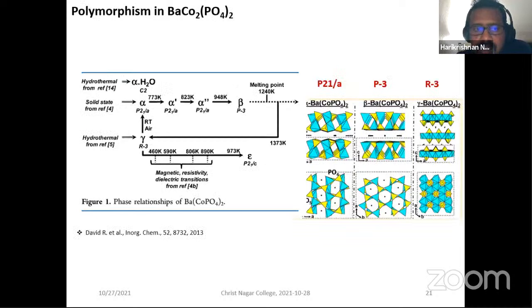Once you get the crystal, you want to look at how the atoms are arranged. One method is to shine X-rays and look at the diffraction data. Literature on this material says that it can have many different structural phases, meaning many different ways of arranging the atoms in space. Three of them are shown here, with three different space groups. We are interested in the third one, called the gamma phase. The other phases are not interesting because they have a very different structure. It is in the gamma phase that we get the 2-dimensional honeycomb layers, which is why we picked that phase.